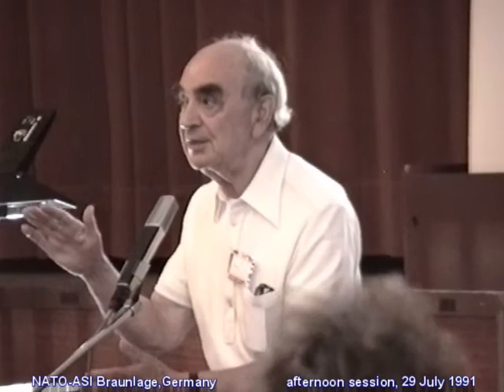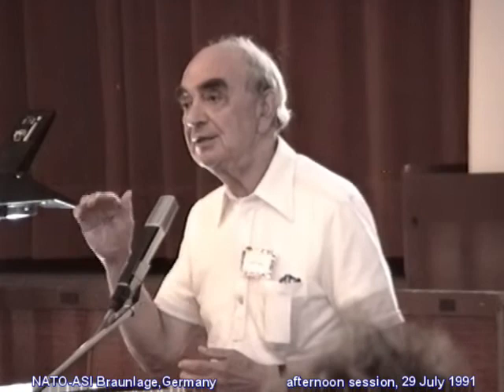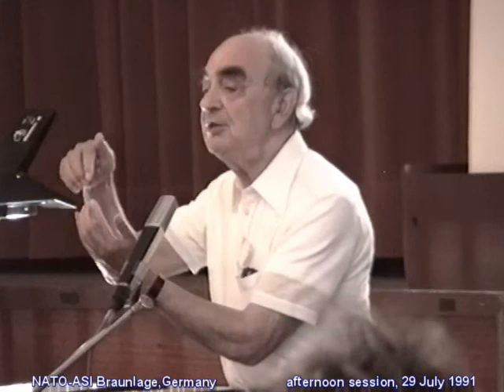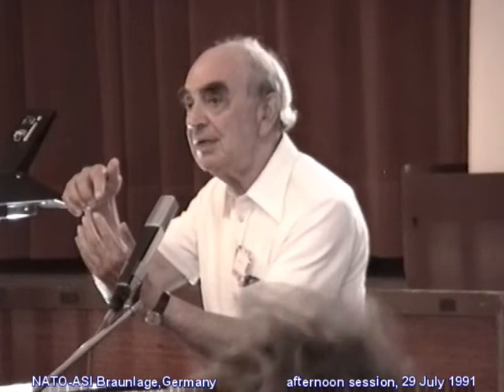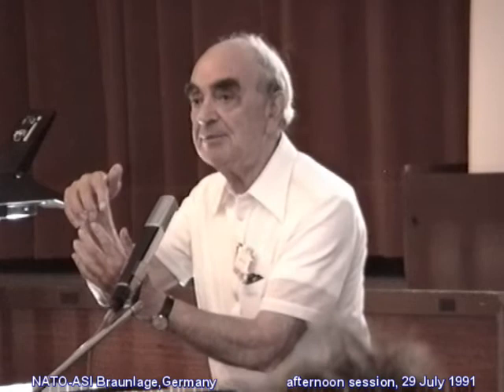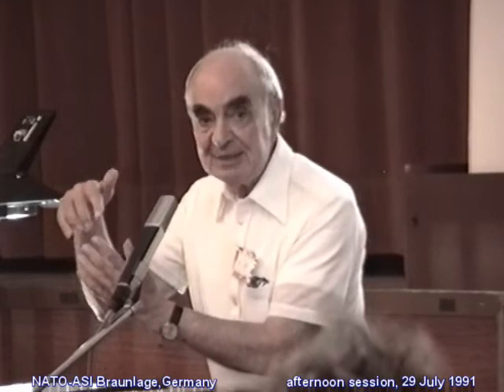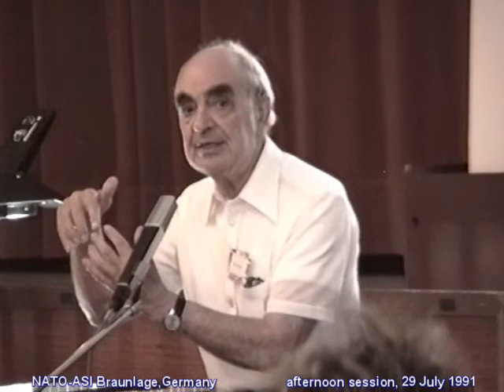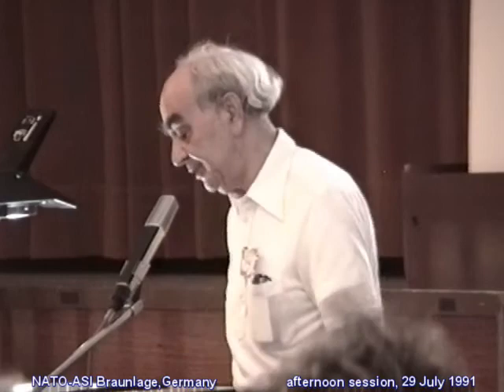But the real point I wanted to make is the distinction between pulling surfaces apart in this way and shearing. It seemed to me that when you're sliding one surface over the other, you're bound to get instabilities in the forces between the atoms and bound to get kicking back and dissipation of energy. That really ends the point I was trying to make: in friction, dissipation is really due to a shear which distorts the structure, and these things flick back from an unstable position and release the vibrations as energy. That's heat. Thank you.